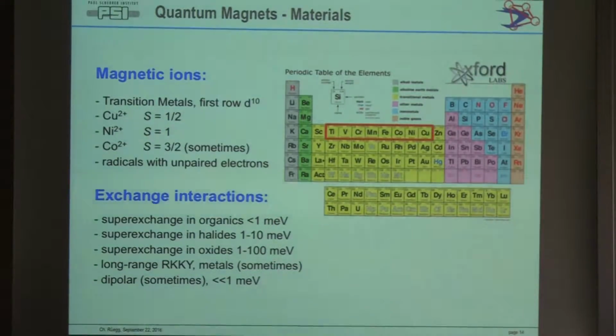So if you want to build up a quantum material, you certainly don't start with iron or yttrium iron garnet. That's spin 5/2, so you never touch this. You start somewhere from copper, which is spin 1/2. You could have nickel, spin 1, then cobalt, and so on. So typically we stay up here, on this side of the bar, if you want.